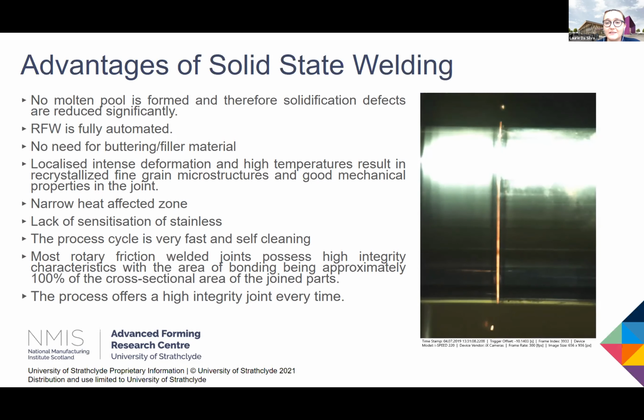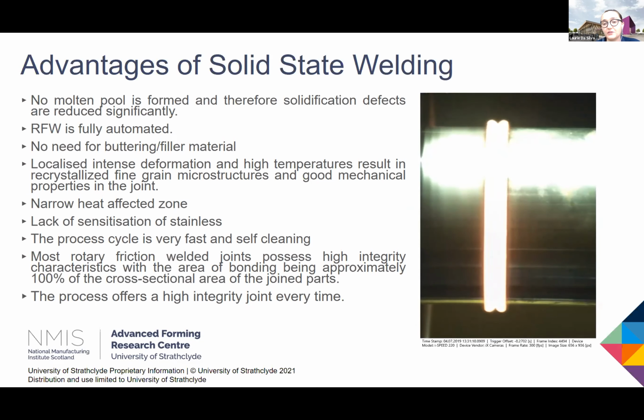And because of the localized intense heat and deformation at the weld interface, you get a very fine, nicely recrystallized microstructure that's similar to a forged joint and gives good mechanical properties similar to the bulk material. You have a narrow heat affected zone. There's also a lack of sensitization of the steel, and the process is very fast, so it's often less than a minute. And it's self-cleaning again, as Richard mentioned, because you can have oxide or debris at the weld interface, and that will be extruded as flash through the OD as we see there, and the ID, which can later be machined. And most rotary friction welding joints are very high integrity. The area of the bond is approximately 100% of the cross-sectional area, and it offers a high integrity joint every time. It's very repeatable.